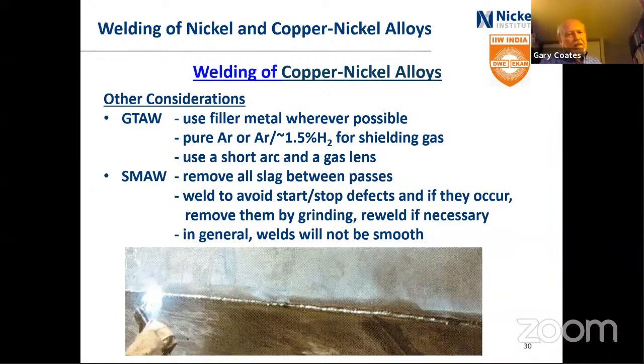Use a short arc and a gas lens. Most people are familiar with a gas lens, and that's just a little screen that's on the TIG torch, also called a diffuser, that causes the gas to not be as turbulent as it would be without that. Shielded metal arc, it's important to remove all slag between the passes, avoid start-stop defects, and if they occur, grind them out, re-weld if necessary.